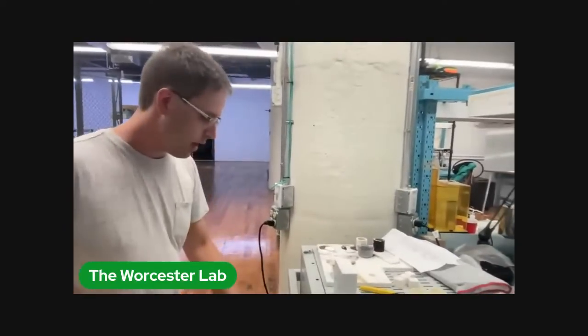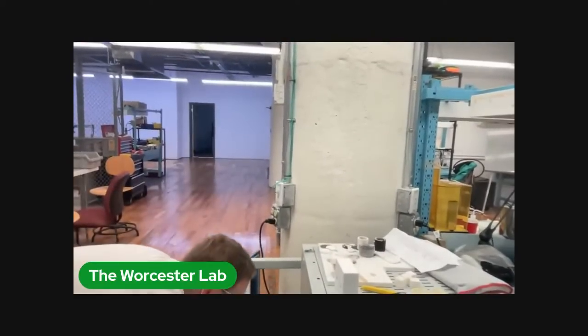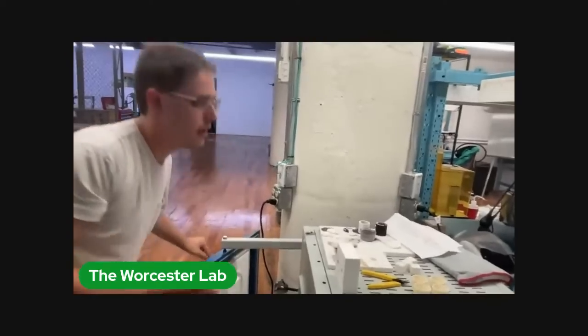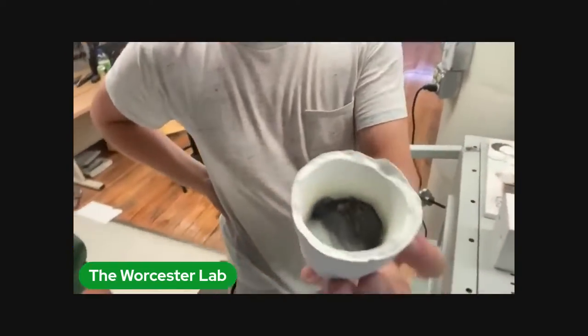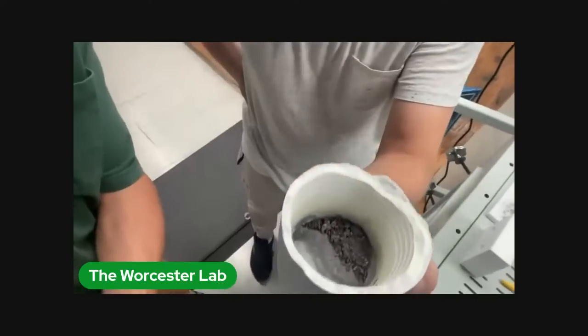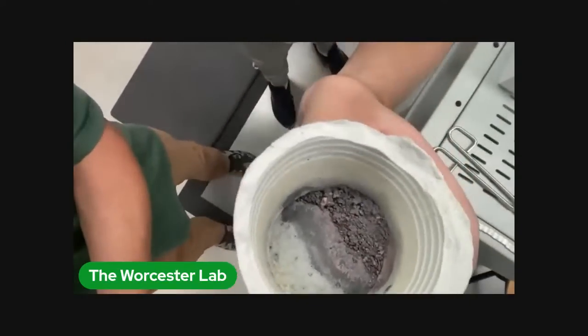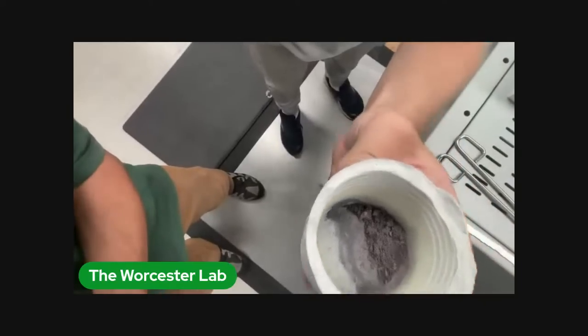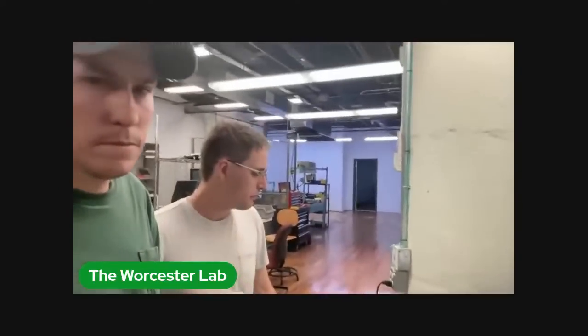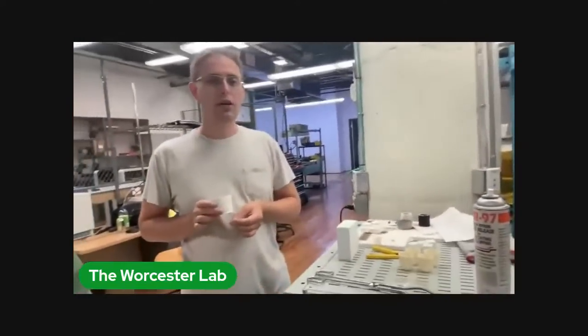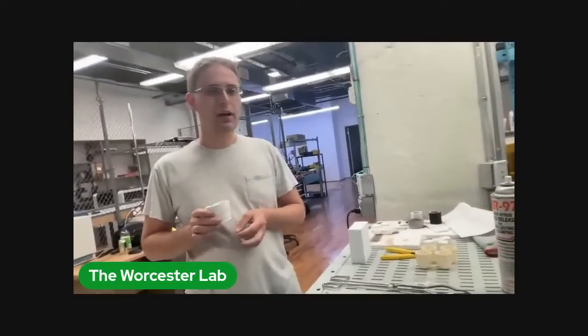We have another batch which is made in the alumina crucibles that we made with the Cotronics material. These have excess copper phosphide, so they have a lot of metallic copper at the end of the run too, which is the red color. The reason we're adding excess copper phosphide is to see if we can produce more lanarkite in a run, because the actual copper phosphide doesn't have enough phosphorus to convert all of the lanarkite into the oxypyromorphite phase, which is the actual superconductor,